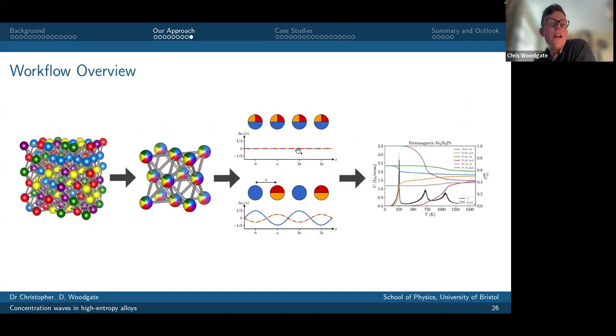So a schematic overview of the workflow is this. We start with the idea that we have a solid solution, a disordered alloy with an underlying crystal lattice. We use the coherent potential approximation to average over the lattice site occupancies and describe this homogeneous effective medium representing the disordered alloy. We then use the language of concentration waves to describe atomic scale chemical fluctuations. And in principle, we can apply this Landau-type theory directly on that formalism and learn about ordering tendencies directly.